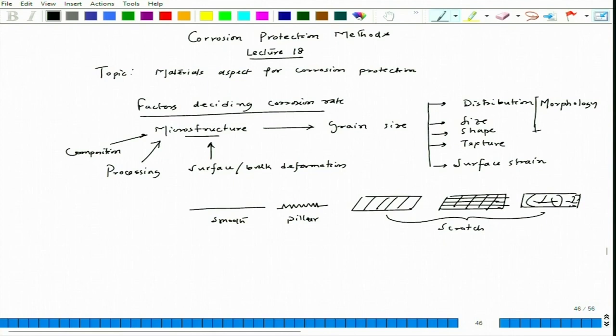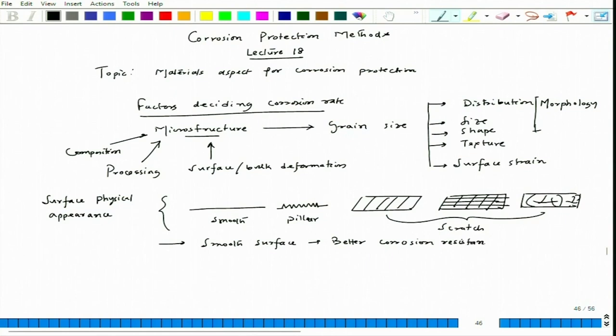Now, we actually have interaction of the material with the environment. So, this environmental factor also should be considered. If we talk about the environmental factor, this comes under surface appearance, or we can say surface physical appearance. For example, the general perception is that a smooth surface gives better corrosion resistance. In fact, some of the corrosion forms can be improved if we make it smooth, for example, cavitation corrosion resistance would increase or be enhanced.